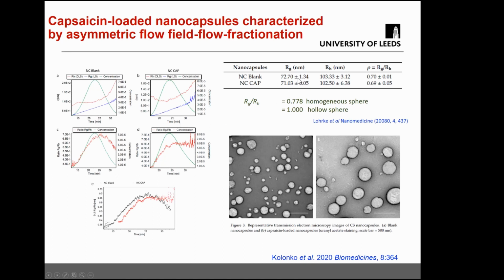By playing with different detectors, we can determine the radius of gyration and the hydrodynamic radius, which are related but not the same. That allows the comparison between the two, as shown on the lower panel on the left. That corresponds to blank nanocapsules on the black lines, and capsaicin-loaded nanocapsules on the red dots. We can see that they are slightly different when we plot the two radii as a function of elution time in the elugrams.